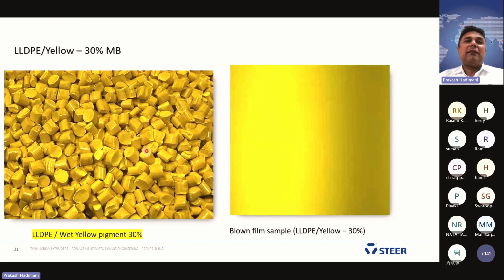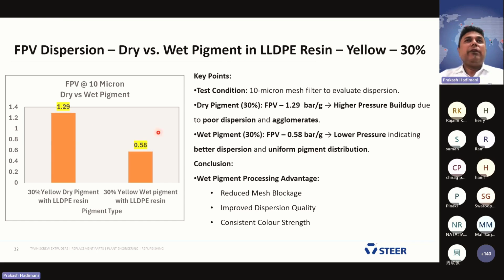We observed well dispersed shiny pellets. And this is the blown film. From the left hand side, we didn't observe any agglomerated particles in the blown film. We also tested filter pressure value. On the left hand side, the same 30% pigments with LLDPE, dry pigment showing 1.29 bar per gram, and the same we used for wet pigments, we observed 0.58 bar per gram.